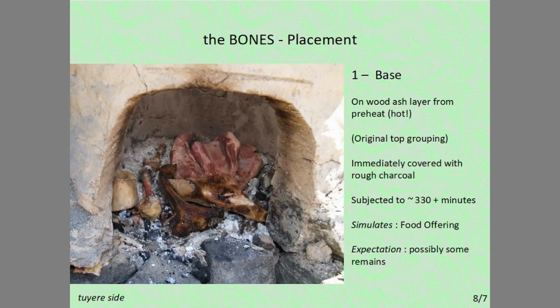How were the bones added to the furnace? The first set was placed in the base on top of the thin layer of ash and still burning charcoal from the preheated fire. These bones were immediately covered with large pieces of rough charcoal, the first ignition process of the furnace itself. This set of bones would be subjected to a total of over 330 minutes of high temperature. It was felt that this simulated a food offering at the beginning of a smelt. The expectation was that there may be some remains, primarily because the heat of the furnace travels upwards, not downwards.